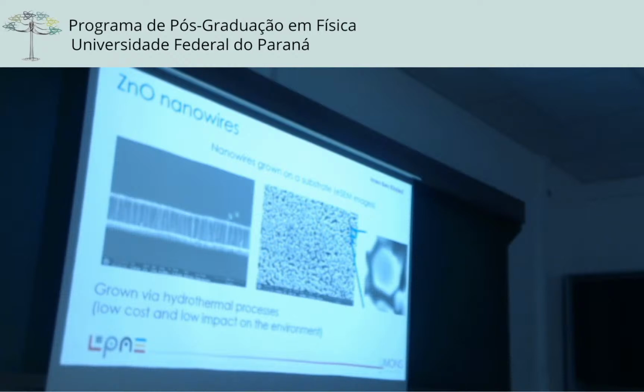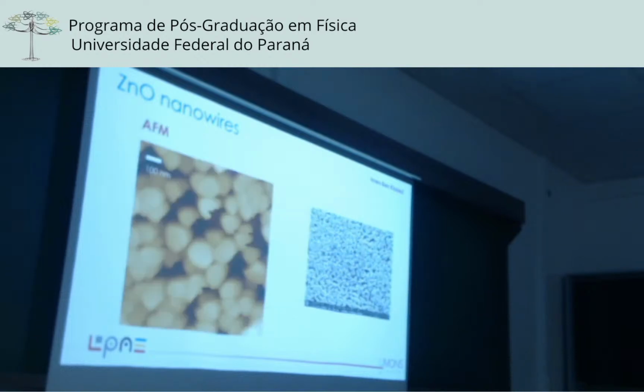So we have those hexagonal nanowires, grown with hydrothermal processes, so low cost, as I said, and with very low impact on the environment compared to the lead-based systems. And this is the AFM, this is the SEM, and you can measure. And now the idea of Imen is to land on one of these nanowires and start to measure individual properties.